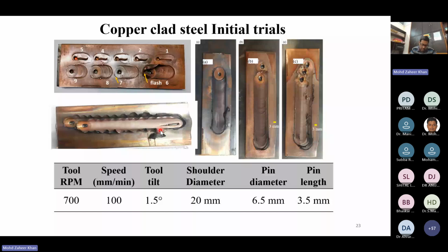The tool material was a tungsten carbide tool with approximately 7 to 10% of the binders. So it is a ceramic based tungsten carbide tool. And as you know, ceramic based tools, when they are being fabricated, some amount of binder is put. So cobalt was used as a binder, and with this cobalt binder, which was approximately 7 to 10%, the tungsten carbide particles were held together, and the tool was created. We bought these tools in the form of cylindrical rods, and the shape of the pin and the length of the pin and everything was created by us in our own lab.